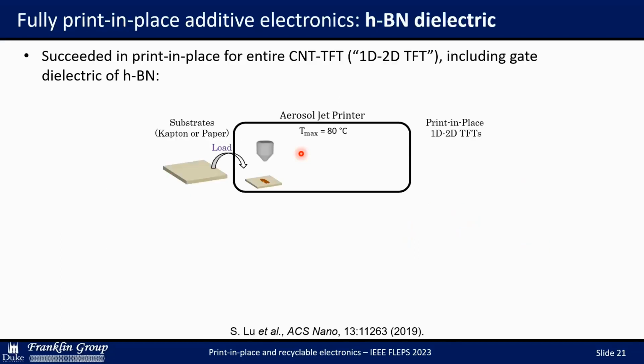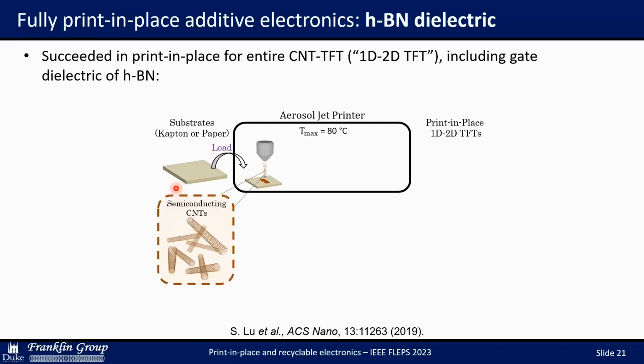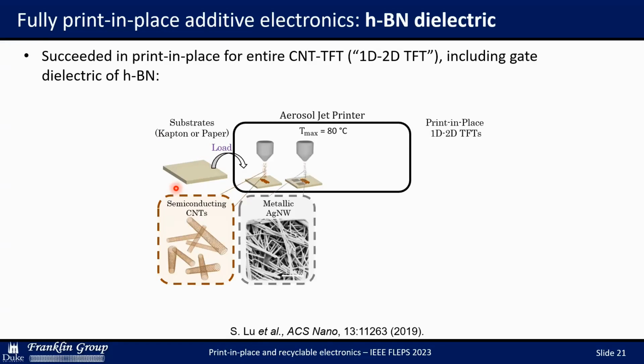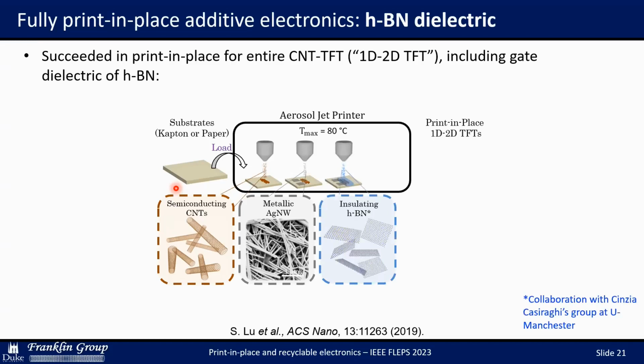So we took this to the next step and added in a printed dielectric layer so that the entire transistor was printed. In this case, we loaded Kapton or paper substrate into the printer. We printed the carbon nanotube semiconducting layer first. Then we immediately after that printed the metallic nanowire source drain electrodes, followed by an insulating hexagonal boron nitride layer as the insulator.